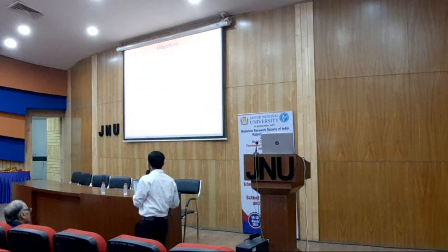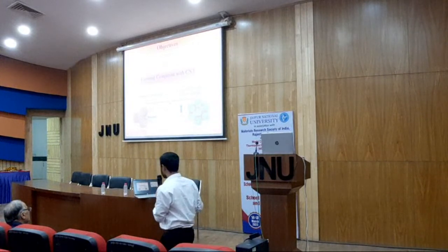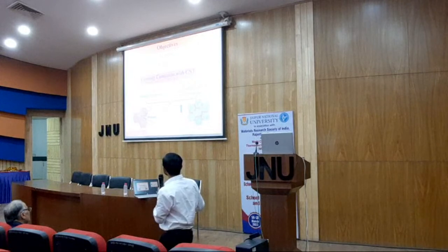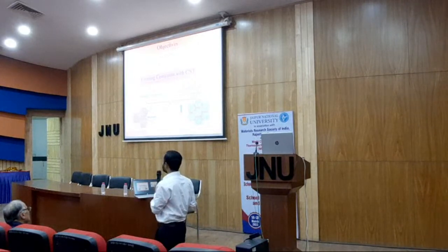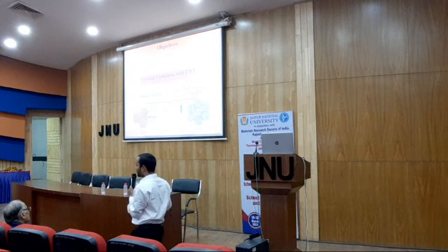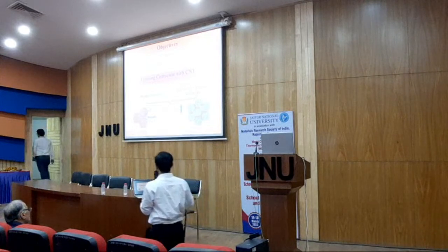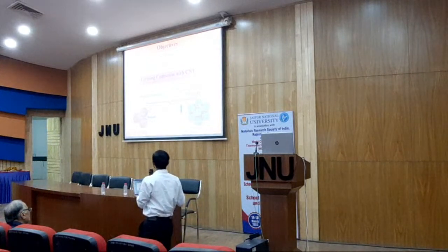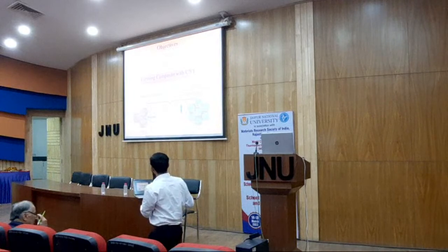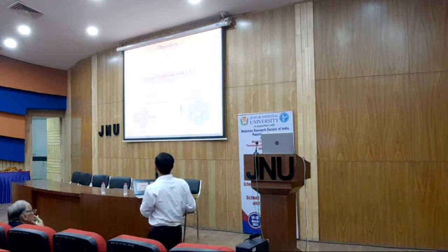Strontium titanate is a very good material because it has a high Seebeck coefficient, but the problem with strontium titanate is its very low electrical conductivity. So people do doping at the A site or B site to improve its electrical conductivity, but that still cannot match the state-of-the-art chalcogenides. So my work is forming a composite with CNT, because that will generate new surface interfaces which will lead to phonon scattering.